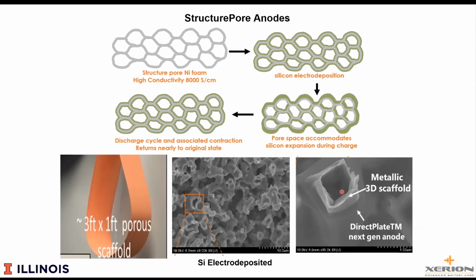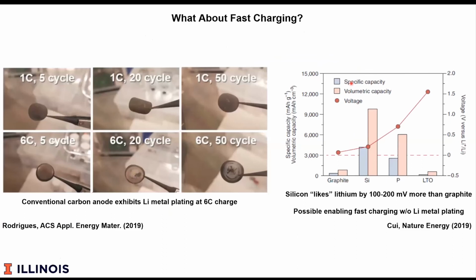The tortuosity remains relatively low in this system because it has such an open pore structure. Although, as I mentioned, at the extremes of lithiation, those pores start to close off, and you have to be careful. But the scaffolds can be made in high volume. So let's think about fast charging.